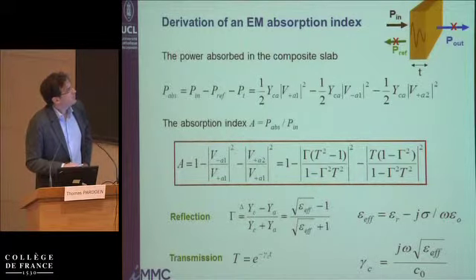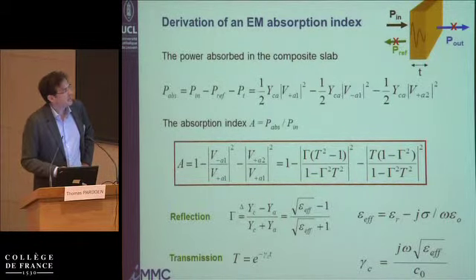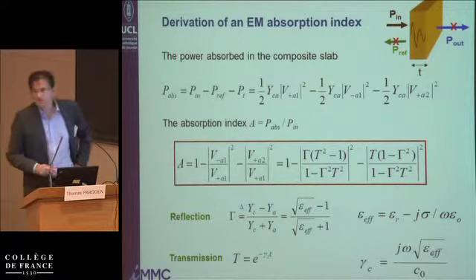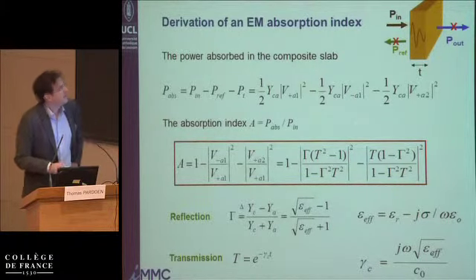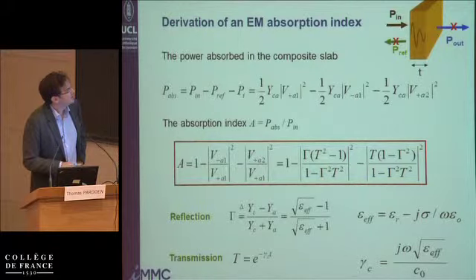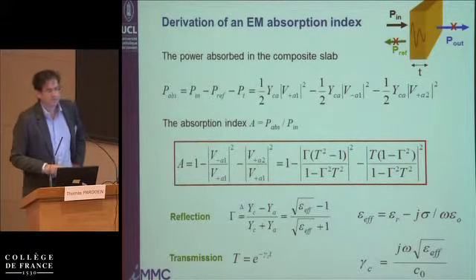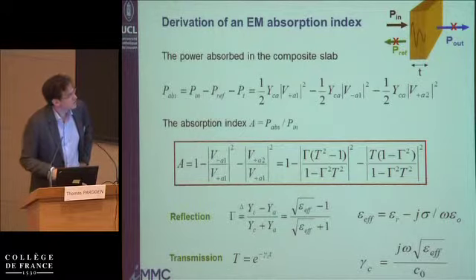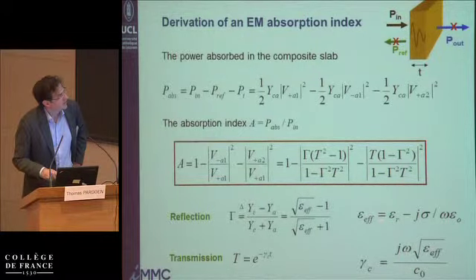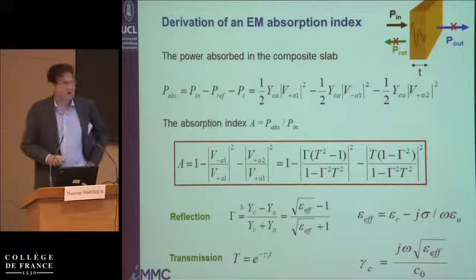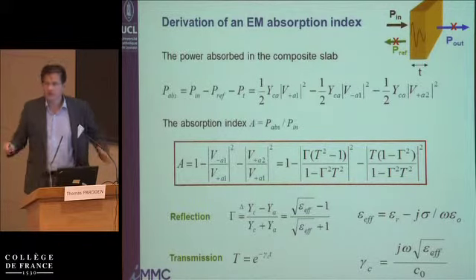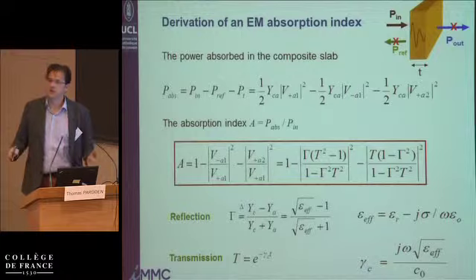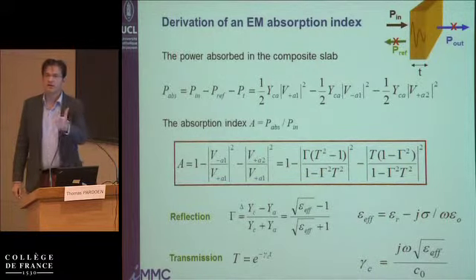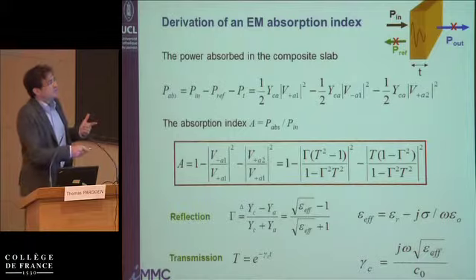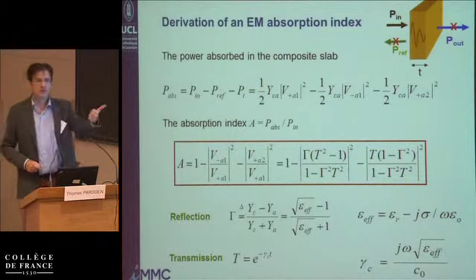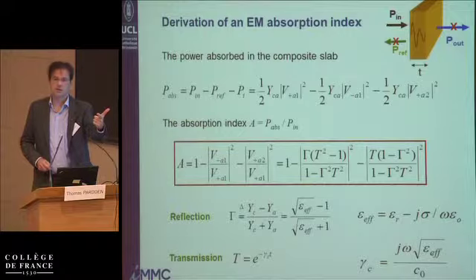And at the end, if you work out the equations, and this is all analytical, you're getting a messy performance index, but still it is analytical. And you see that this absorption index depends on the reflection and the transmission. And the reflection and the transmission, they are both connected to the effective dielectric constant of the medium. And at the end, the effective dielectric constant is a function only of the dielectric constant and the conductivity of the material. So this is a function of dielectric constant and electrical conductivity.